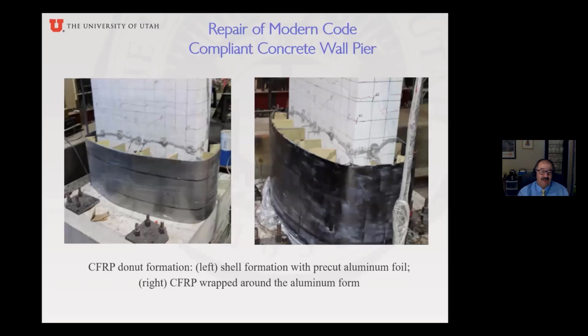So how do you make the shell? Well, we use aluminum foil and some wood form, and we made this big circular or elliptical tub, as we call it, the tub, instead of a donut in this case. And that makes the formwork. And then you wrap this aluminum foil with the carbon fiber sheets, and then you can take out the wood and the aluminum foil when, in about 3 or 4 days, this carbon fiber actually hardens. It hardens very hard. It's almost like glass. You have to be very careful. You can cut your fingers.